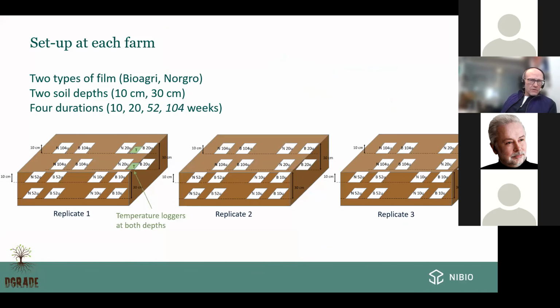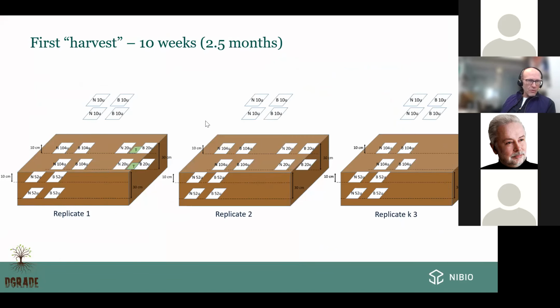This is a little bit how the setup looked at each farm. So we buried the two types at two different depths and replicated this four times for four consecutive harvests. Then we repeated this three times for experimental replicates. And then we buried some temperature loggers along with the pouches. And then we gradually removed them.